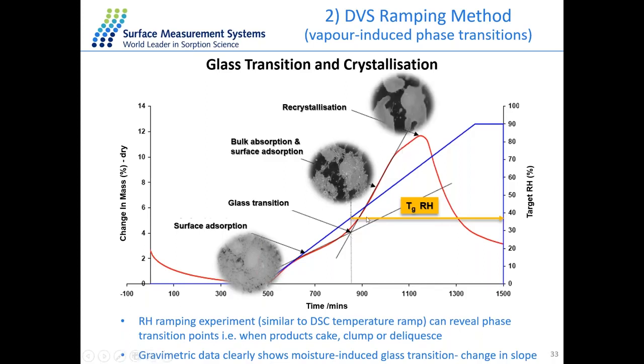We can also look at what happens when you increase relative humidity further, where we have another change in our sample. This is the recrystallization stage of the material. Because the sample is undergoing crystallization, we have a tightness of the packing and a drop in mass uptake. And then we can see that our sample has fully crystallized.